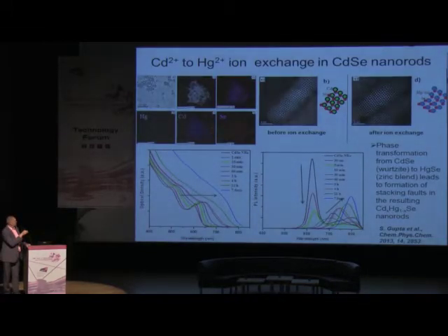We can also start from nanorod-like particles, in that case cadmium selenide rods, and if we do a very similar reaction, mercury exchange, then we actually find out something interesting in terms of phase transformation of those nanorods. Cadmium selenide original rods are wurtzite type, and it seems that they convert gradually into mercury selenide zinc blende nanoparticles. And by that, the emission in the near infrared appears as well.